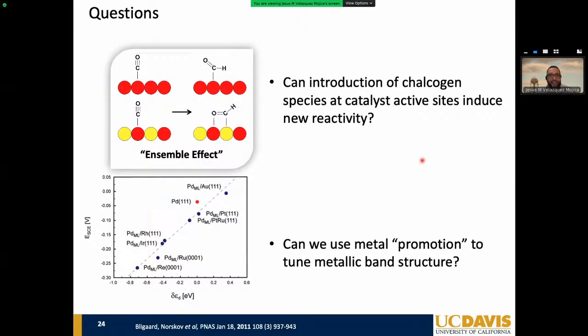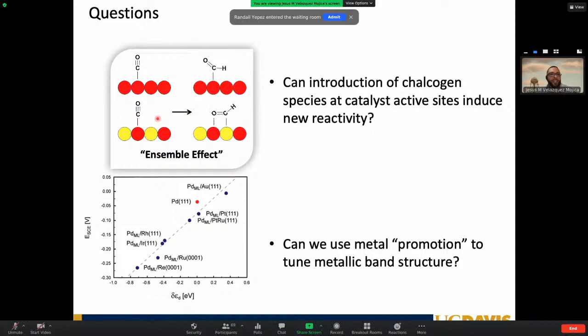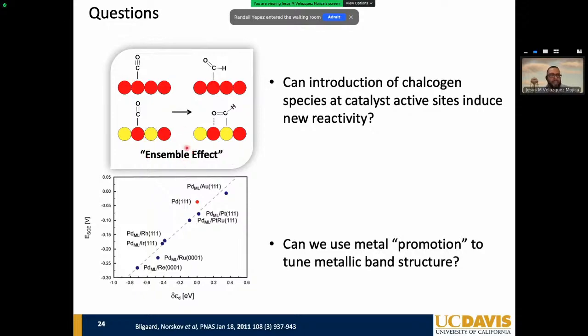And what type of impact could it have? Well, by just introducing the chalcogen, I already hinted that we could perhaps give these intermediates like carbon monoxide an opportunity to have some interesting bonding configurations that is actually known in our world as the ensemble effect. So by having chalcogen versus perhaps a monometallic surface, we now have what could potentially be the power of controlling whether or not you have a monodentate or a bidentate bonding configuration for intermediates. That's just by introducing the chalcogen. But now when you intercalate an element within this framework, then we could talk about metal promotion. And what that basically means is we can fine tune the metallic band structure in ways where we could control that Sabatier principle, that Goldilocks binding affinity that is so important for you to be able to trigger multi-proton electron transfer reactions.